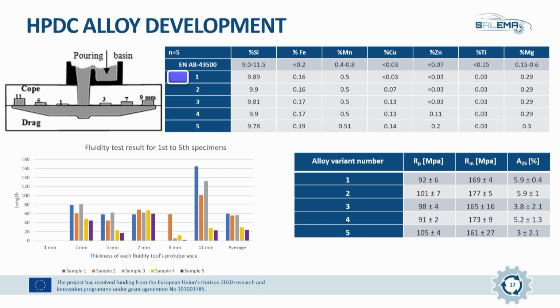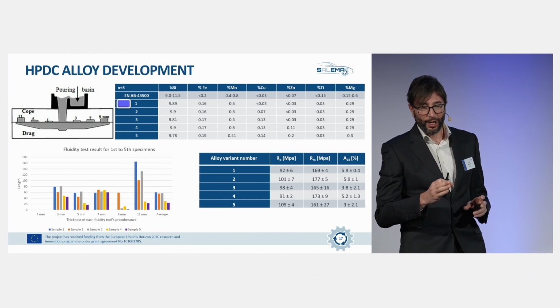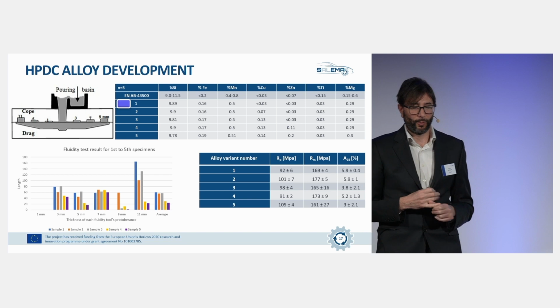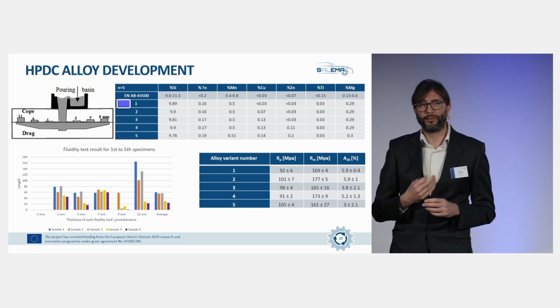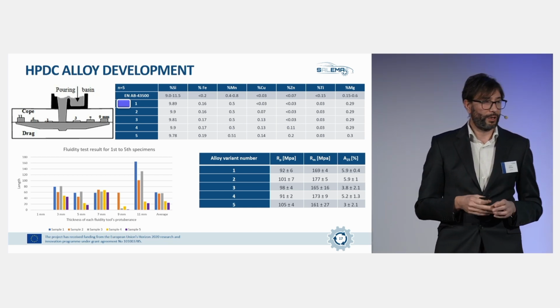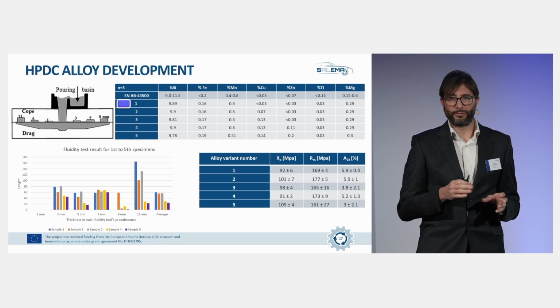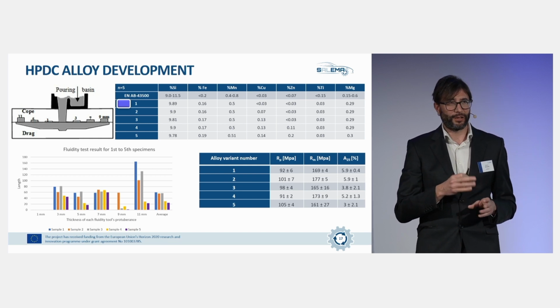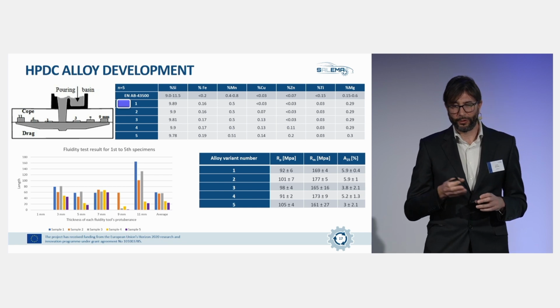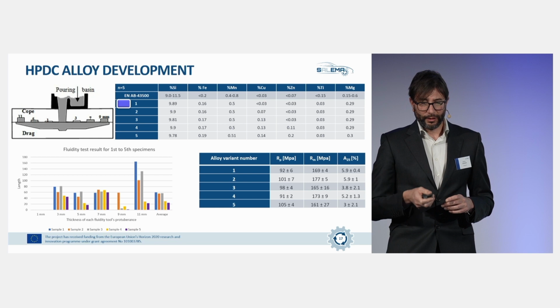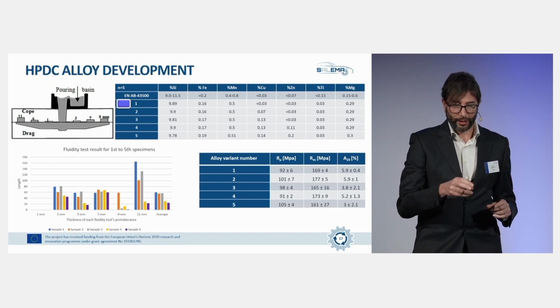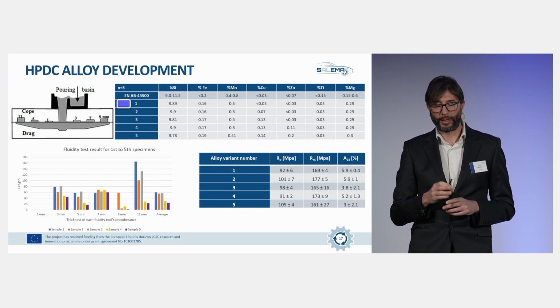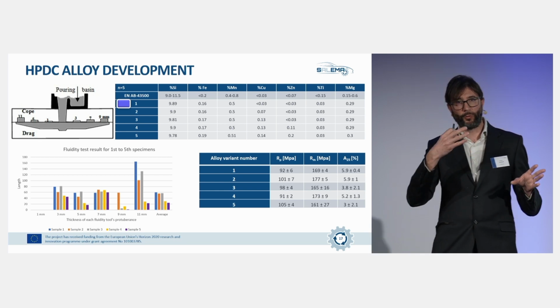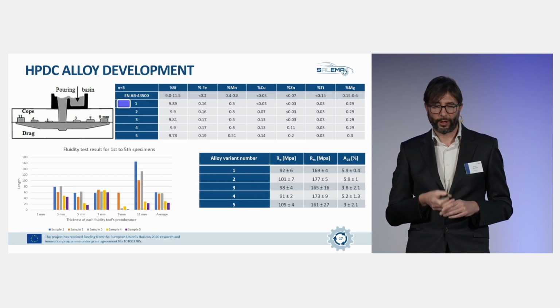To assess the performance of this alloy, before going into the high pressure die casting process, we did a general screening with these 5 alloy variants, where we measure flowability of the alloy with a mold and a technique defined at SALEMA, and that is currently under standardization. We are right now publishing a pre-standard, a CWA, that is going to be published within a few weeks. And with that, we were able to check how small variations in chemical composition could affect alloy flowability and then the ability to fill the part and to get a good part with the high pressure casting process.